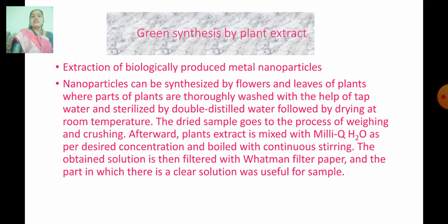Then this plant extract is mixed with double distilled water as per the desired concentration and boiled with continuous stirring. The obtained solution is then filtered with Whatman filter paper, and the part which is a clear solution is used as a sample. So it is a very simple, easily available method, and there are a number of antibacterial and medicinal properties in that plant, and therefore we can use it.